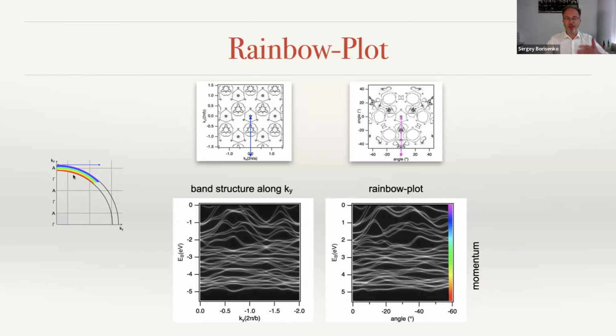And this inset actually shows why this is so, because the blue arrow corresponds to this. This is now a view from the side. This is a photoemission thing. People draw such Ky, Kz plots very often to find out where V0 is, where this inner potential, where they cut the momentum space. So this is one of those. But here, in addition, I plotted again the rainbow. So this is the portion of the K space which is probed in the typical photoemission experiment in the hν approach. And this is the band structure calculation.